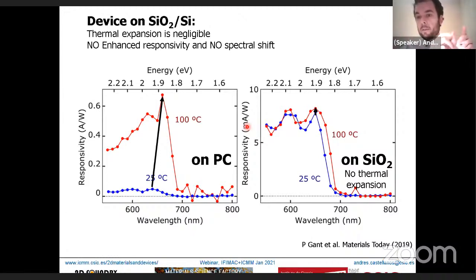One set of devices is fabricated on polycarbonate, where you have a large thermal expansion, so you have change in temperature and change in biaxial strain at the same time. And we have this other set of devices fabricated on silicon oxide.